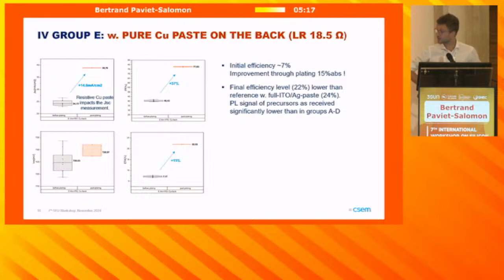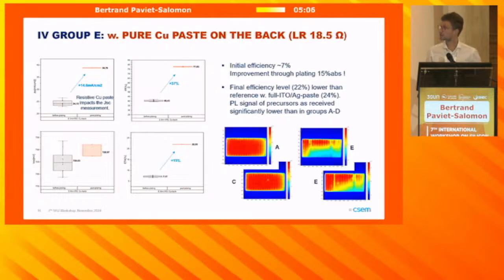So it's very encouraging. I have to say that those devices in particular are plagued by an unexpectedly low VOC, which was actually the case already before the plating, and which stems from the processing stage, because they featured pretty poor PL signals compared to the devices in the other batch. So globally, there should be room for improvement to have a pure copper approach with those devices.